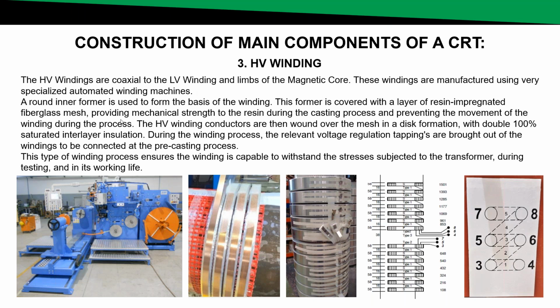The mesh actually acts as rebar for concrete for the resin. So it just adds mechanical strength and reduces cracking of the resin under normal operating conditions. The HV winding conductors are then wound over the mesh in a disc formation with double 100% saturated interlayer insulation. During the winding process, the voltage regulation tappings are also brought out to be connected at a later stage. This type of winding process ensures windings are capable of withstanding the stresses subjected to the transformers during the testing